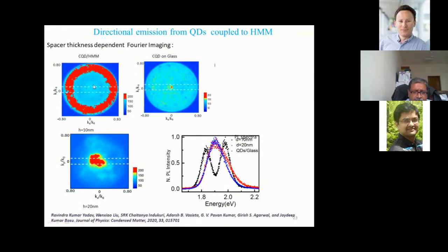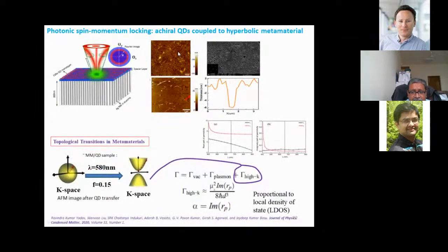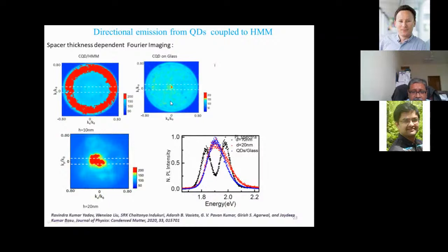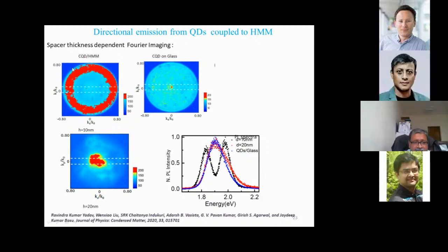So first of all, when you look at it in terms of Fourier imaging, exactly the same thing here but on glass, you don't see anything interesting happening, right? It's very boring, no structure. When you put this on the metamaterial, you see this kind of strong ring, which indicates a particular preferential wave vector where there is intensity, which is indicative of directional emission.